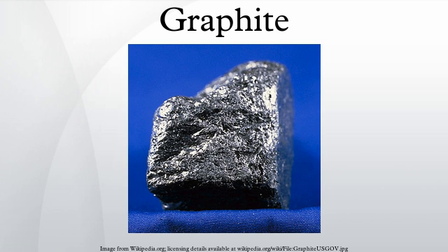The use of graphite is limited by its tendency to facilitate pitting corrosion in some stainless steel, and to promote galvanic corrosion between dissimilar metals. It is also corrosive to aluminium in the presence of moisture. For this reason, the U.S. Air Force banned its use as a lubricant in aluminium aircraft, and discouraged its use in aluminium-containing automatic weapons. Even graphite pencil marks on aluminium parts may facilitate corrosion. Another high-temperature lubricant, hexagonal boron nitride, has the same molecular structure as graphite. It is sometimes called white graphite, due to its similar properties.